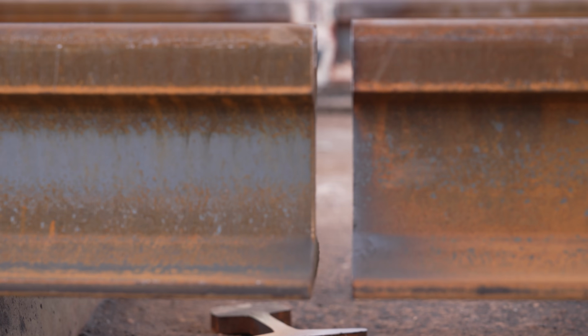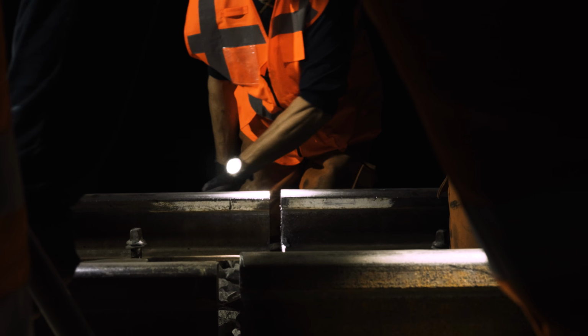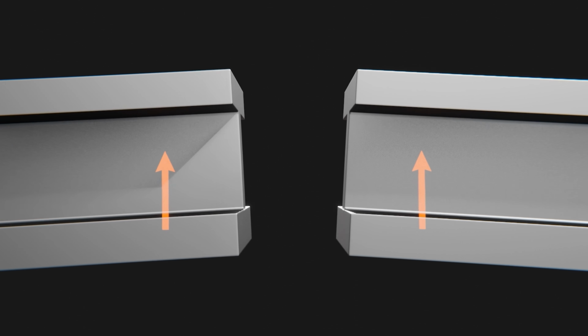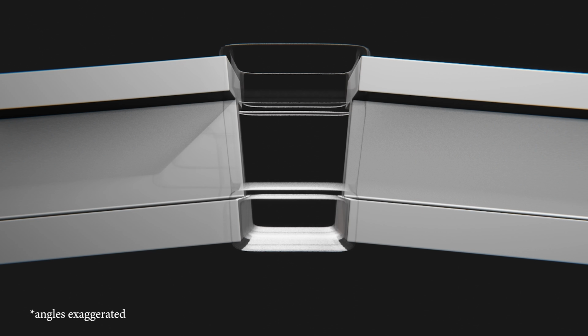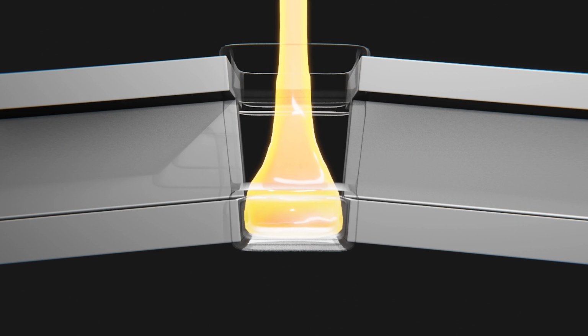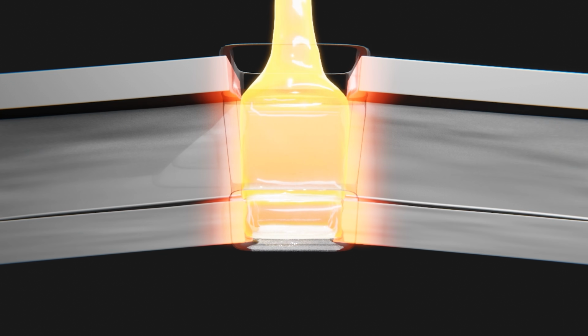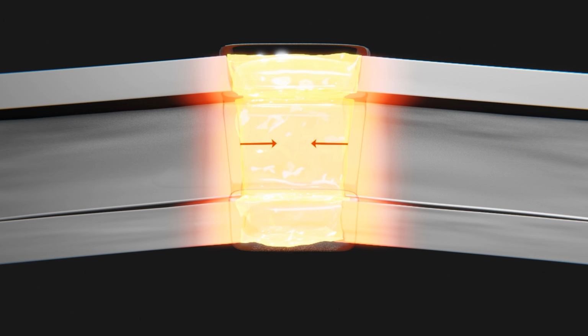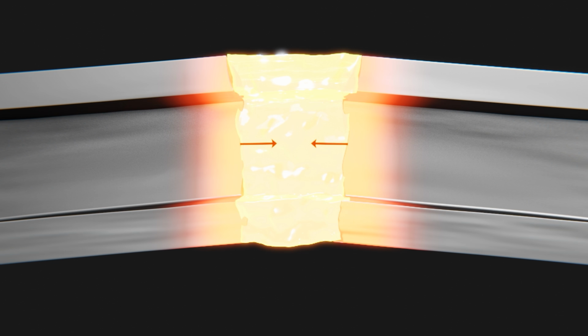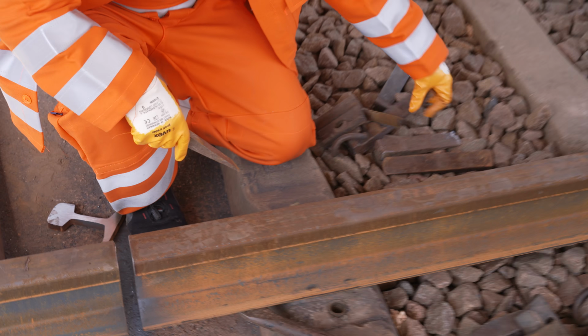The next step is to line up the rails so the weld will make a seamless connection. Both rails have to be angled slightly up toward the gap. This is because when the liquid thermite steel is poured in, it will contract as it cools, which creates an inward pulling force. But that force won't be the same everywhere. Since there's more metal at the top, there's more force pulling the rail together there. So that's why the rails have to be angled up, so that after the liquid steel contracts, the rails will be perfectly flat. Now you take one of the wedges and put it a little bit under the rail.